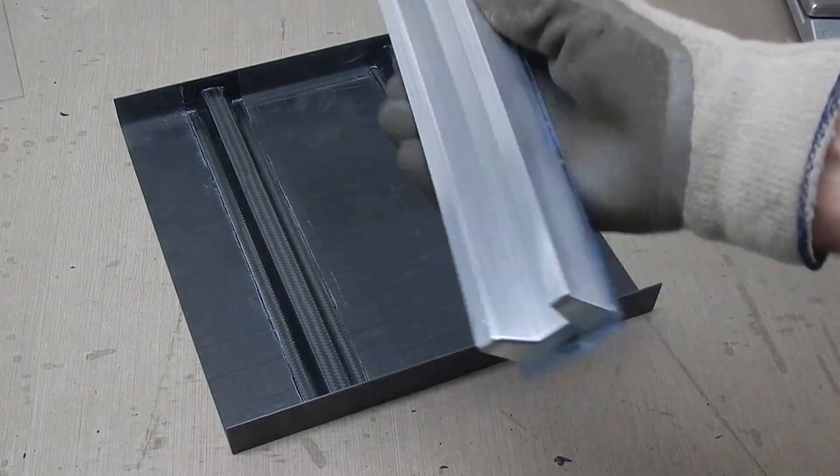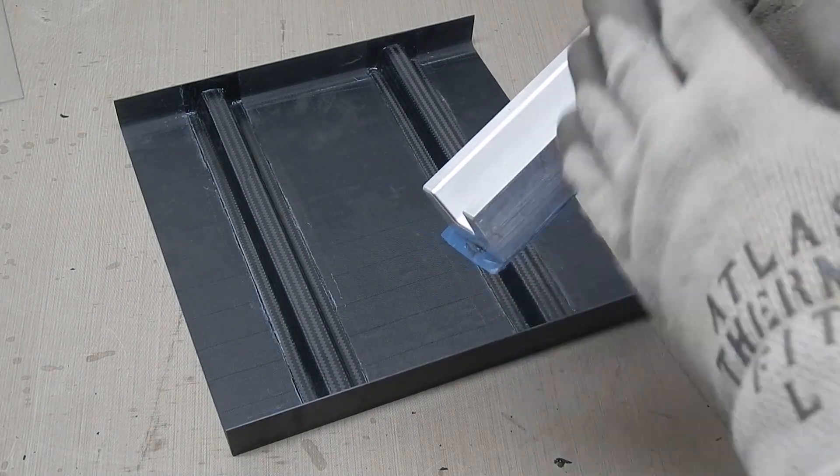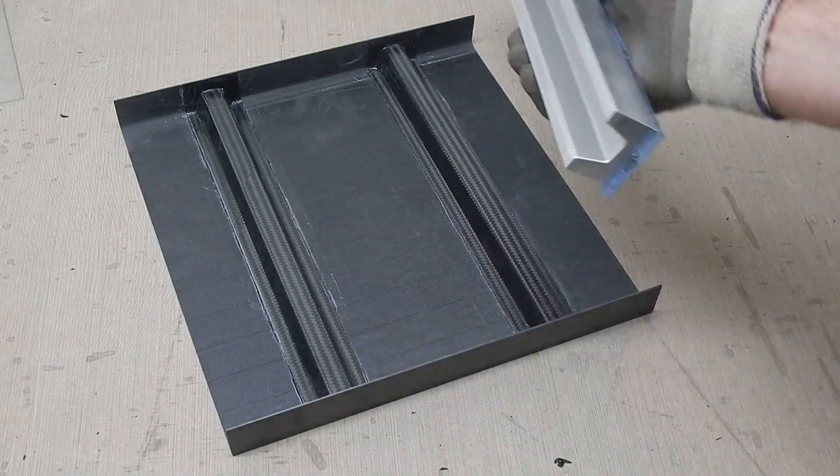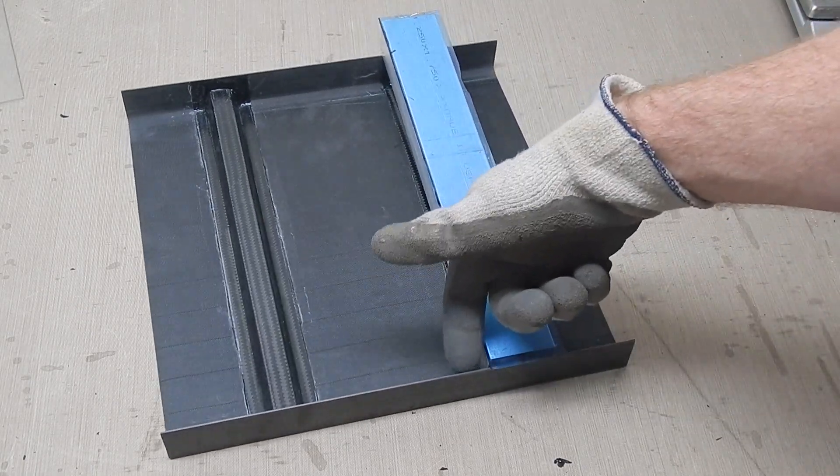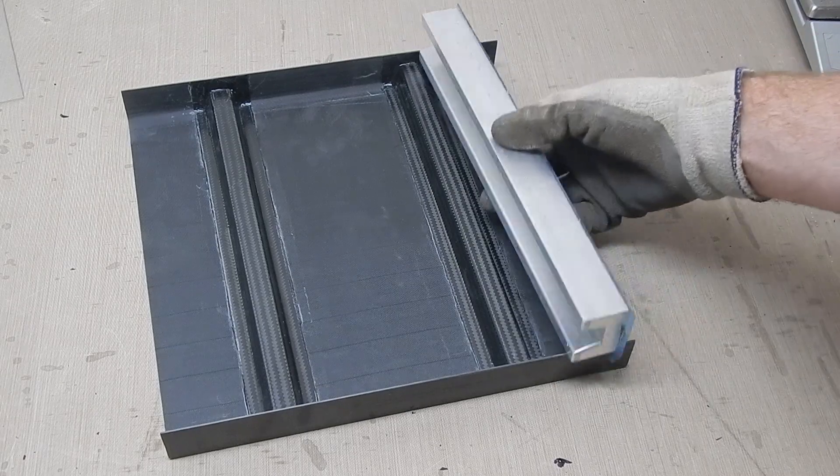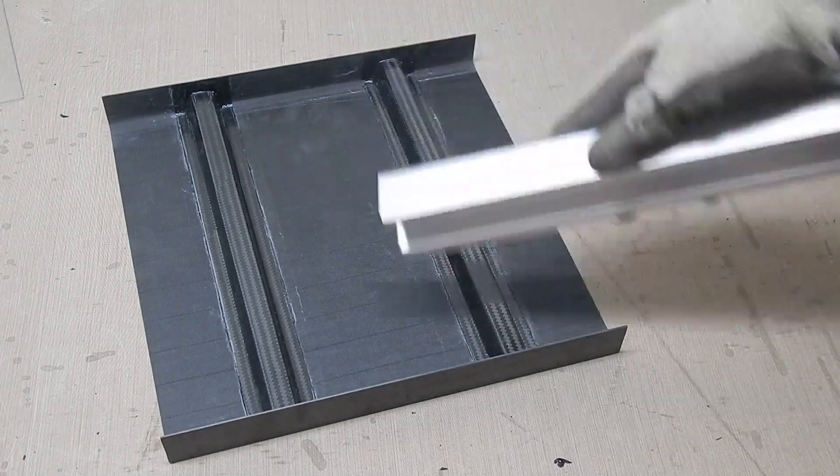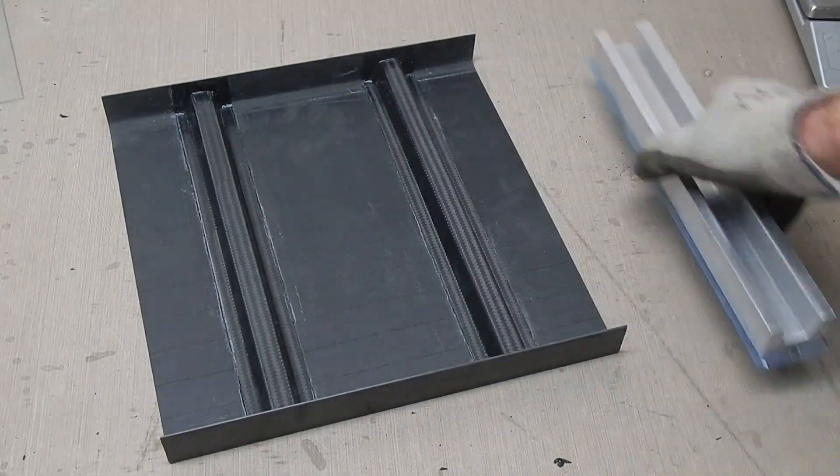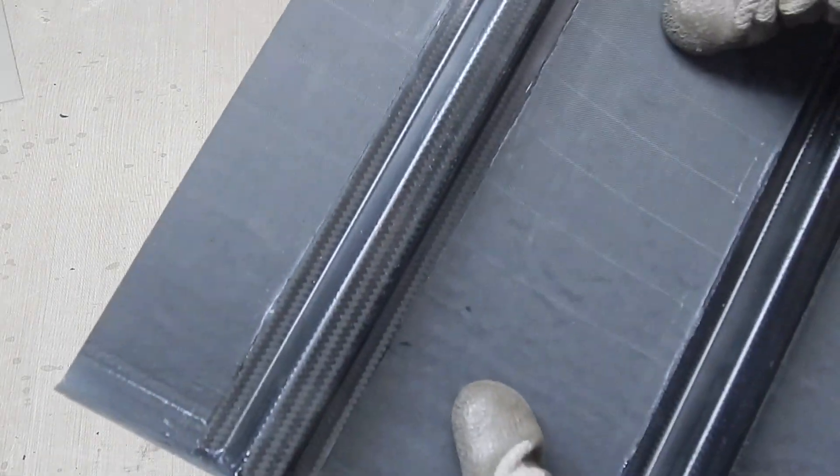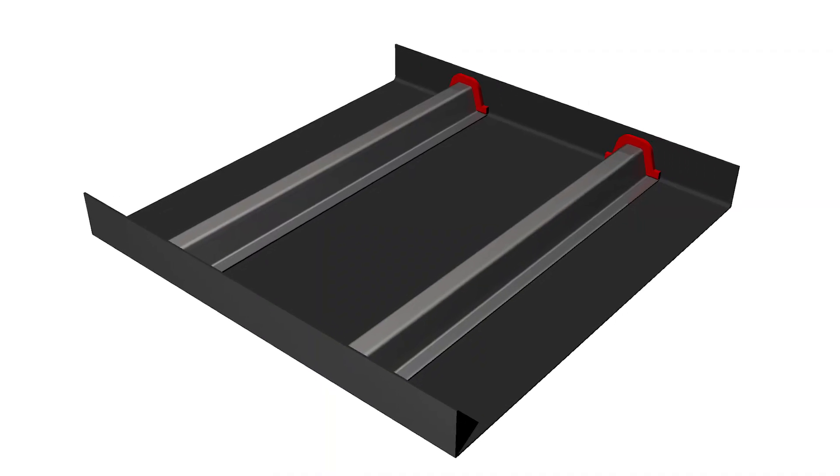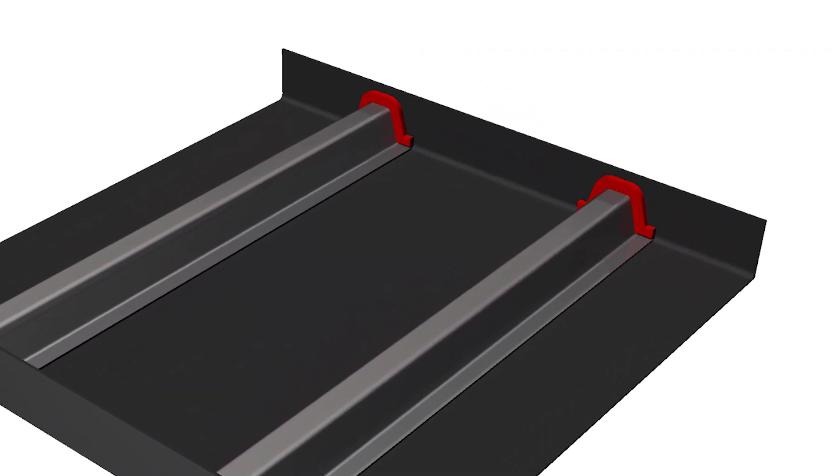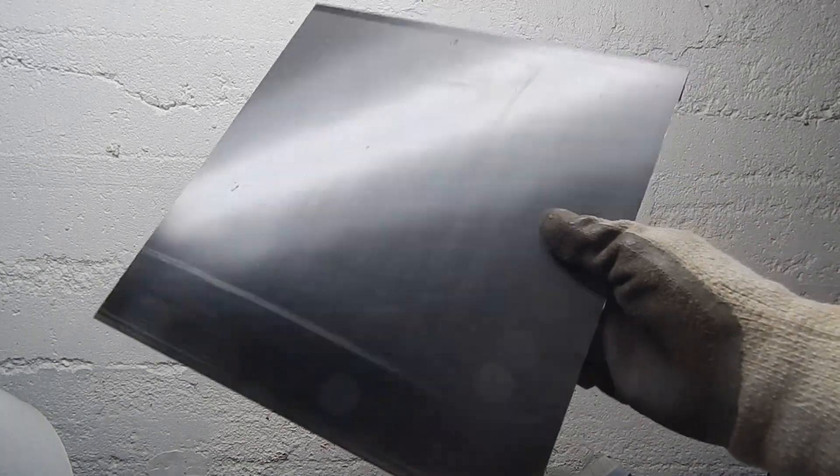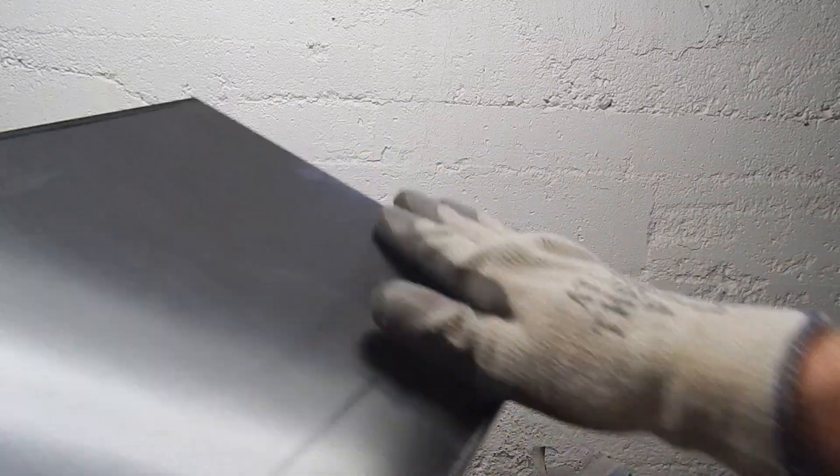So here's the part of the mistake. When I made this, I made it a foot long because I had not imagined I was going to use it with these channels. So the channels I made were longer than they needed to be. What I could have done had I been clever, is to make this aluminum mold shorter by the thickness of the laminate, plus a little of the area, the length in between the flanges. And then molded in more laminate around the end of the aluminum mold, like shown here in red. So that the laminate would bond. There would be room to bond it onto the flanges. And that would have been, that's what you should do. Because leaving them open like that, it's a bad idea.